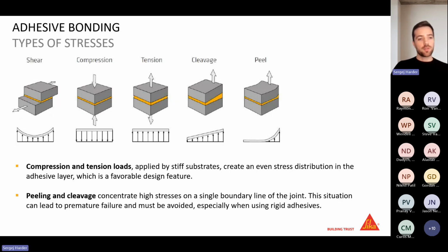Now, a second part to consider when modeling with adhesive bonds is the stresses that you have acting in the adhesive bond. So with this overlap design, you have the shear stress inside your bond, which is okay for adhesives. Just one thing to consider here is that most of the time, the nominal strength that you get, for example, for the shear lap test, does not consider the stress peaks at the edges. So in reality, even in these test results, you will see much higher stresses in the adhesive, and you cannot just consider it to be a homogeneous distribution of the stresses.